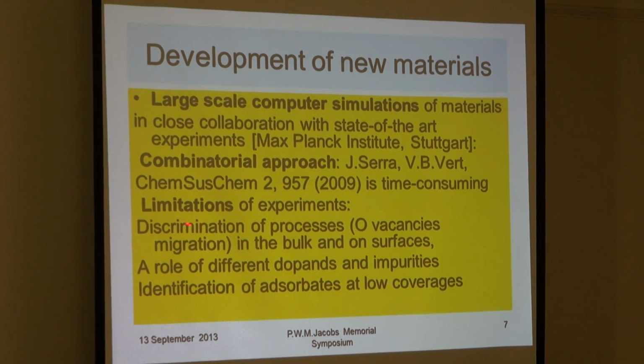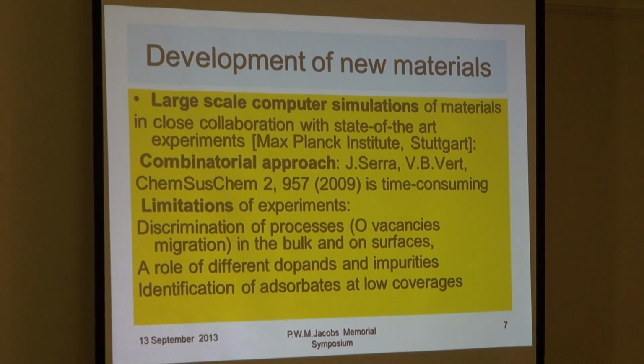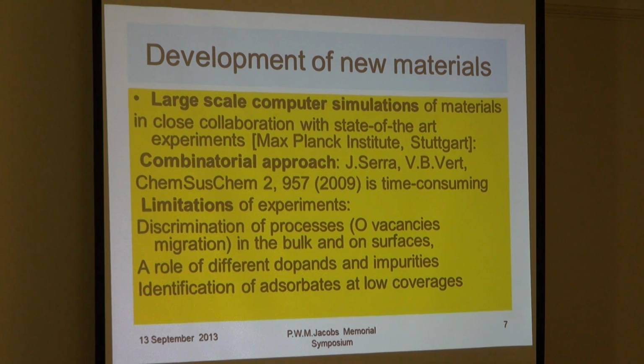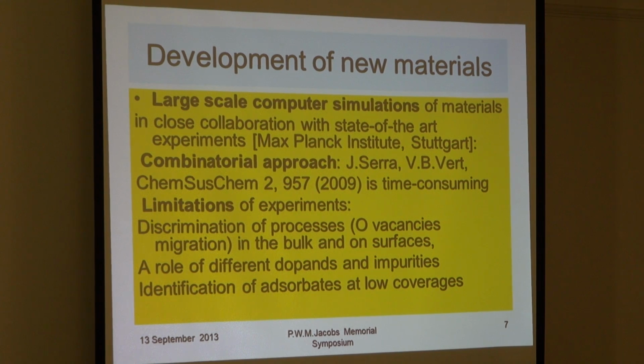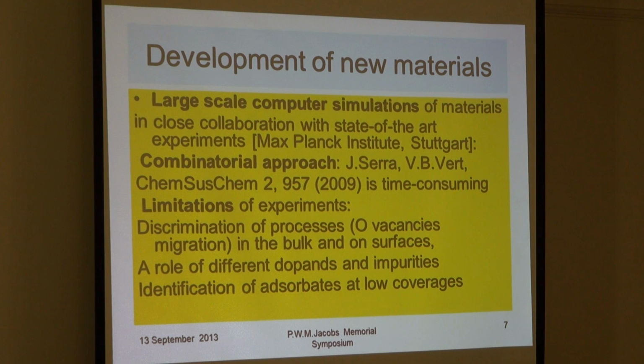First, you can't discriminate the surface as a surface from the bulk or near surface. And in the case of oxygen reduction, you need to understand the reaction between surface vacancies exactly and adsorbed oxygen. Experimentally, you can't distinguish vacancies in the subsurface area from the very surface. And second, theoretically you could easily look at the different roles of different impurities and dopants, and also identify adsorbates at low coverages, which is a challenge experimentally.